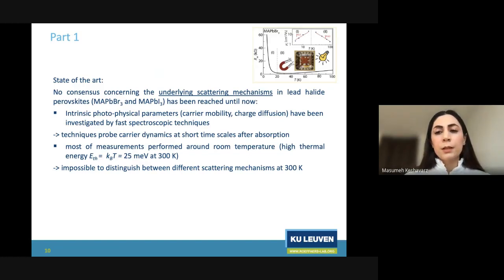So in part 1, the state of the art when I started this project was that, first of all, there was a lot of various numbers reported for mobility, and the measurements were mostly performed by fast spectroscopy measurements, which in a very short time, you put a lot of intensity of the light into your system, and then you look at the relaxation of the charge carriers, and like that, you can extract the mobility. However, you can also affect the system by the intense light onto your system. Most of the measurements were performed at room temperature, where you cannot access the scattering mechanisms in your system because of the high thermal energy.